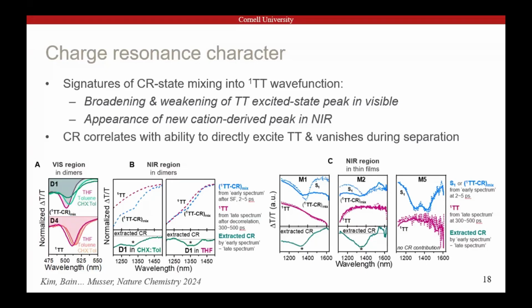And this was great because we did have a problem with this observation, which, the whole point of singlet fission, at least nominally, is to make solar cells better. And the reason that this was able to be a fundamentally new discovery in singlet fission photophysics 60 years after it was first discovered, we'll see we can directly excite it, is because it came from what seemed like a silly experiment. As spectroscopists, we don't usually pump a material where it doesn't seem to absorb light.